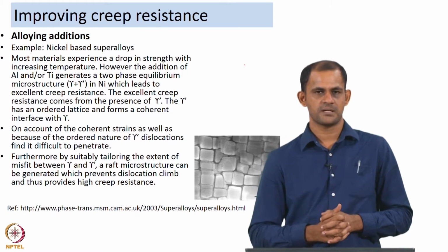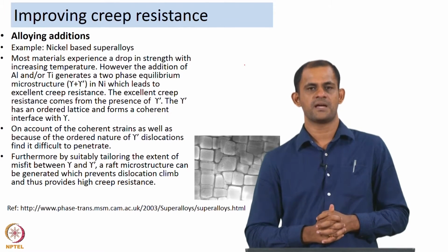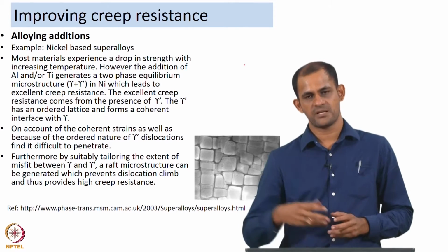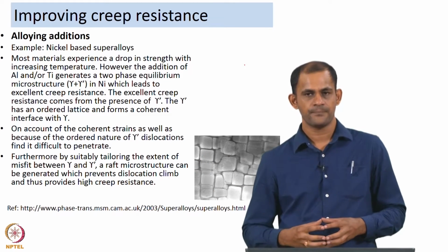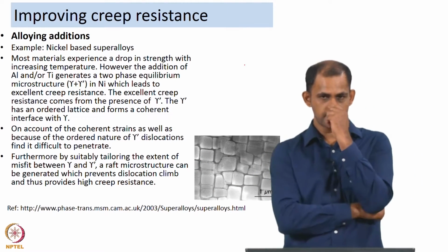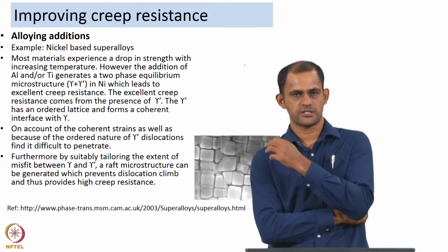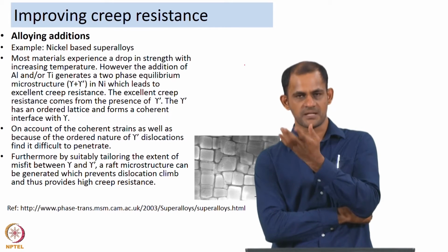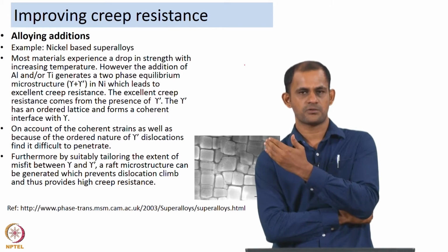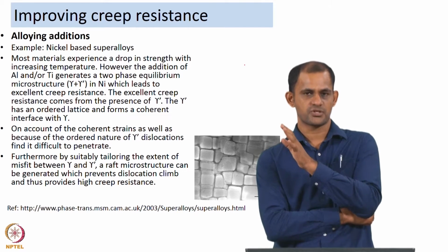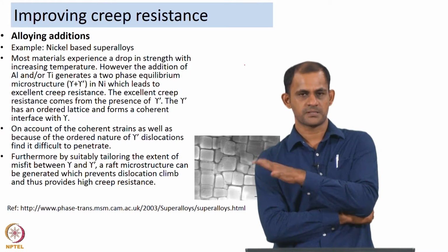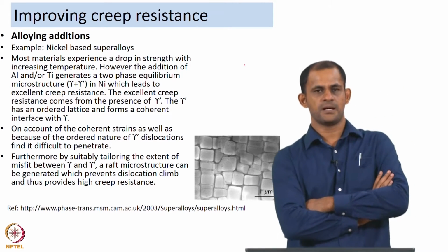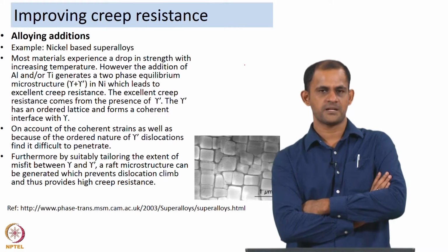Let us talk of nickel based superalloys, which are used in gas turbine engines, especially in the high temperature region, and the reason is these alloys have excellent high temperature strength. So, compared to most materials which experience a drop in strength with increasing temperature, nickel based superalloys continue to retain their strength till higher temperatures, and this is on account of the addition of aluminum and or titanium.